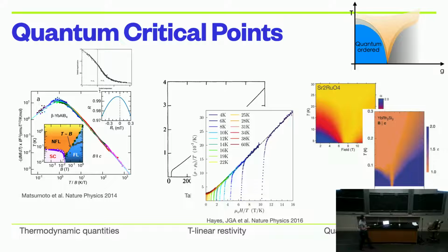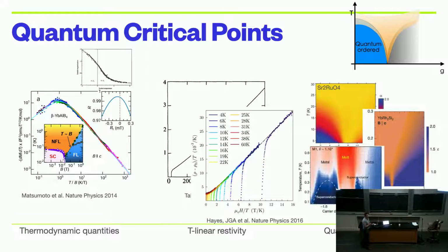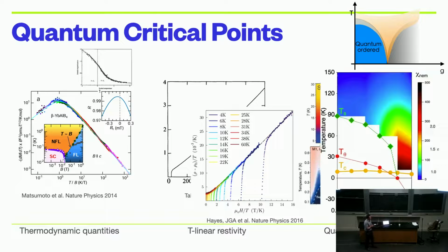This other system, ytterbium rhodium two silicon two, has a similar kind of critical fan of fluctuations that lead to apparently strongly T-linear behavior again. The moire systems have similar kinds of phase diagrams, again indicative that there's a critical point with a collapsing energy scale that's connected to the presence of superconductivity. Over and over it comes up, and there's no exception to the example that I showed you, which was the nematic susceptibility, the response of these iron-based superconductors to strain, where you now have this diverging susceptibility right near a critical point.